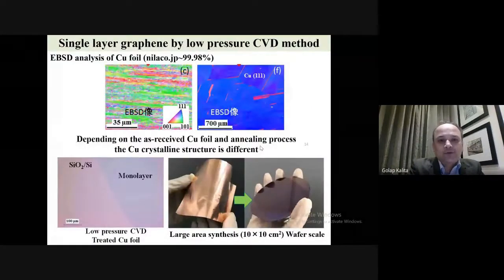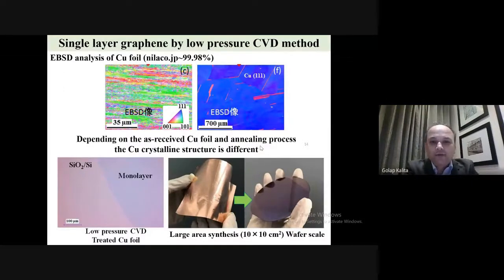If you see, this is a transferred monolayer graphene on silicon oxide, and we can now grow this monolayer graphene at wafer scale. We grow it first on resolidified copper foil, then the monolayer graphene is transferred to a silicon oxide wafer. This is a 4-inch wafer. We can transfer by chemically etching the copper foil. Of course, we first give a polymer support on the graphene, then we etch the copper foil, then we transfer to the silicon wafer or any other arbitrary substrate. We can transfer the graphene.